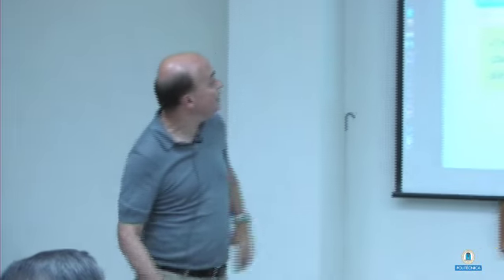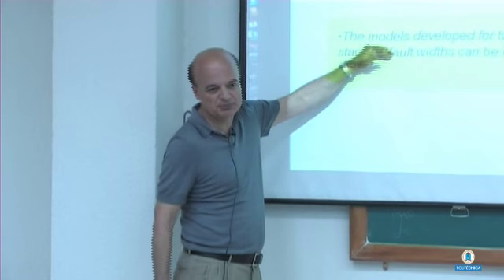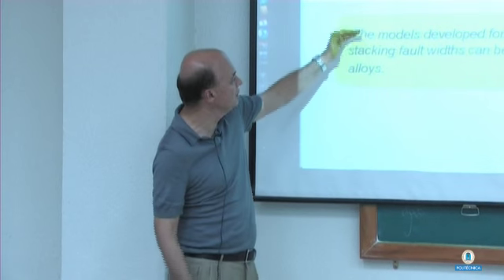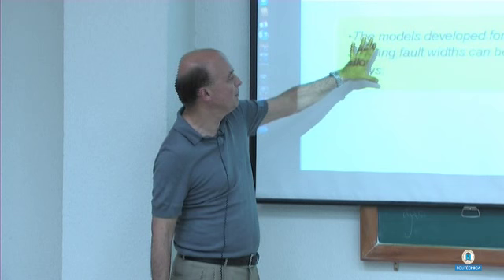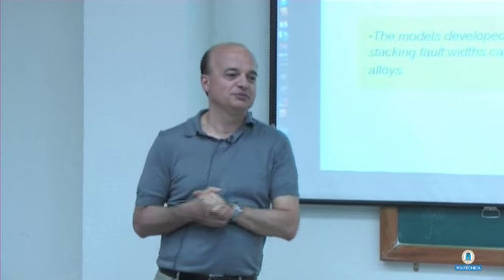Again, no twinning in this case. This is my final slide. Stacking fault width is determined by the gamma surface, not by intrinsic stacking fault energy alone, which is again what we teach our students. The models developed for twinning stress, which I focused on primarily in this talk, and briefly stacking fault widths, can be utilized to design new alloys.